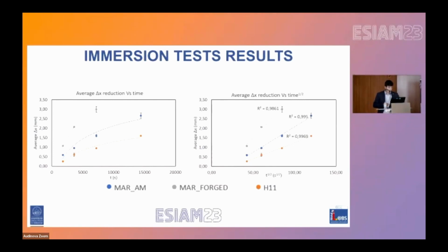Here you can see on the left side the plot of the thickness loss versus the immersion time. As can be noted, the maraging AM sample presents a better corrosion resistance with respect to the forged one. In fact, it was not possible to evaluate the thickness loss after 4 hours of immersion due to the high dissolution of the forged sample into the molten aluminum.